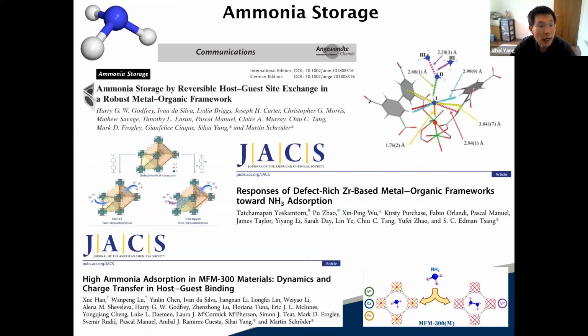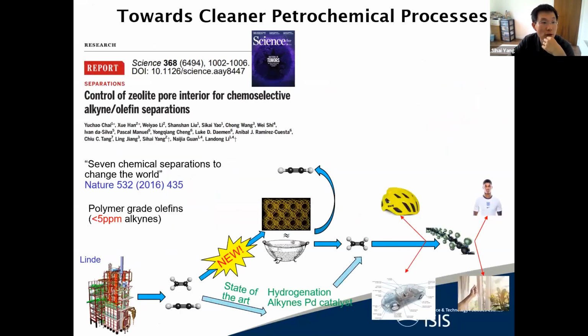Ammonia storage is another very important area of research, as previously mentioned by colleagues. This is treated as a green source of hydrogen, so really a very multi-billion pound business in the future. It's between our group and colleagues in Oxford. We developed a range of MOF systems that can achieve reversible high capacity storage of ammonia to aid their transport, long distance or short distance. In particular, such systems, published here, have a massive unit cell that could be 10,000 cubic angstrom. So this WISH diffractometer is really playing an important role there.